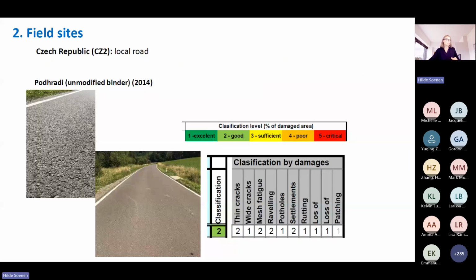And then I have a last section to show you, which was from the Czech Republic. It was again a local road, with a binder from 2014. And in this case, we got an evaluation of the performance from a consultant, which divided it into 5 levels, as you can see here, depending on the amount of damage that they observed. And this road got a severity 2.